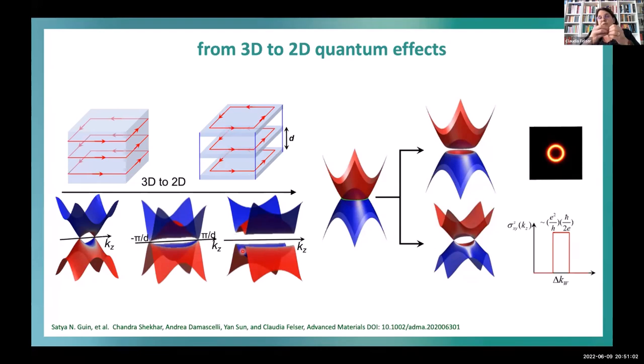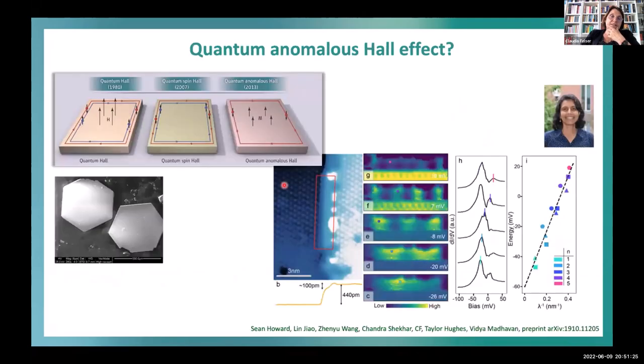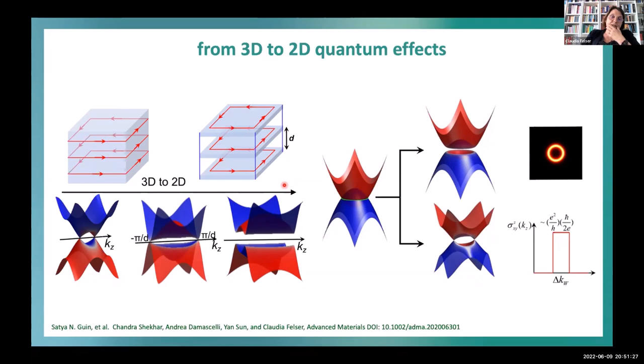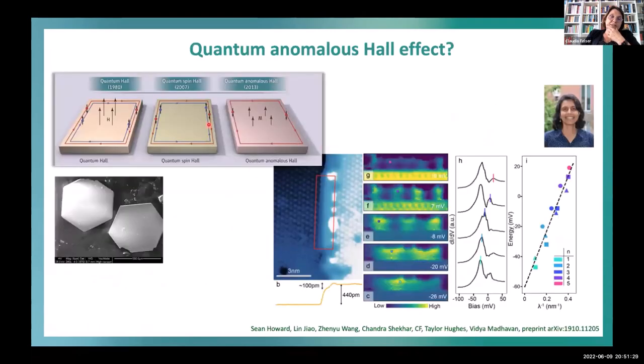You can say, if you bring the Weyl points to the edges, you end up with a magnetic topological insulator. So the k-vector cuts between the Weyl points are quantized, and if you have a large Fermi arc, you have a very large area of quantization. And here, if we reduce the interaction between the layers, do we see already evidence for a 3D quantum Hall effect in this material? And indeed, if you simply divide the anomalous Hall effect by the number of layers, you're already quite close to quantization.